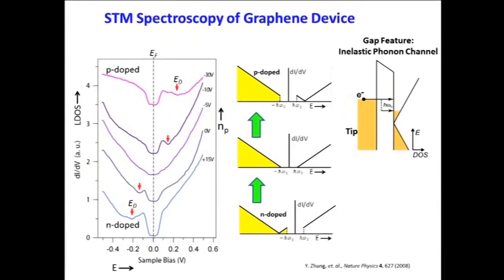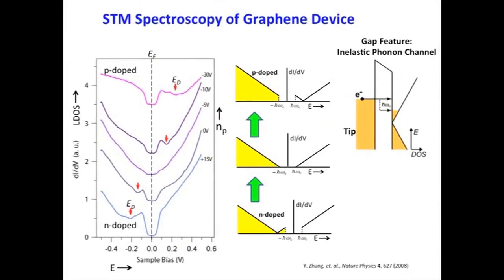So that tells us that it's not a band structure feature of graphene. It's some kind of excitation. And what we believe is happening is that this is a sign of, it's not a true gap, but it's a sign of inelastic tunneling, phonon-assisted inelastic tunneling.